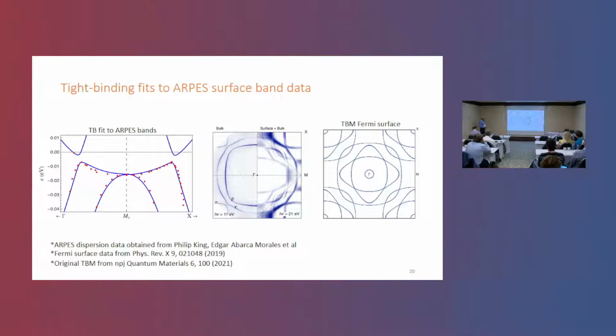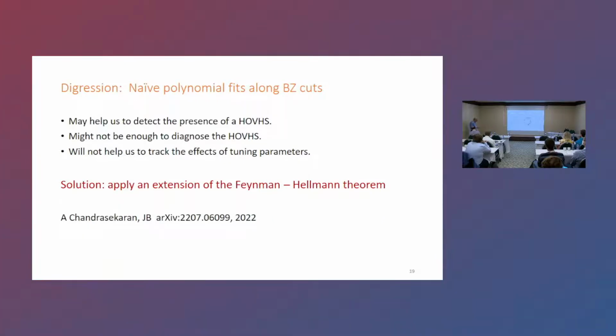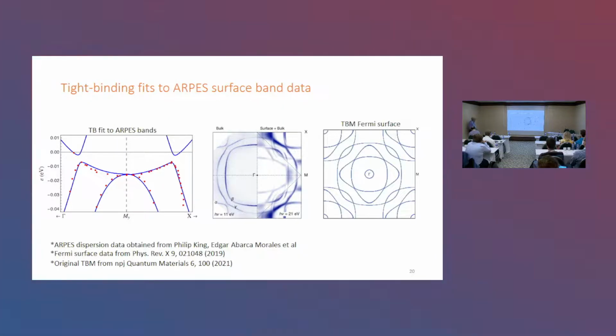And what we found with a tight binding model from quasi-particle interference work is that we can have two different saddles. One is at a new point, this one. The other is created by this one, okay? With a very tiny difference in the location of the two saddles.